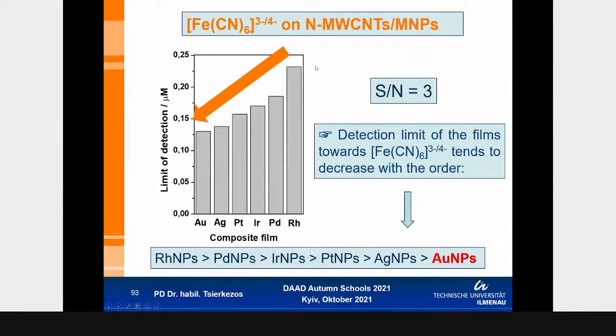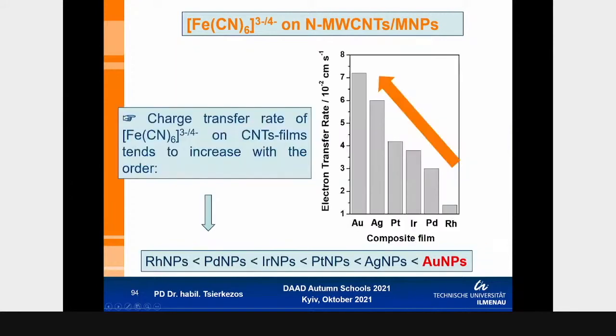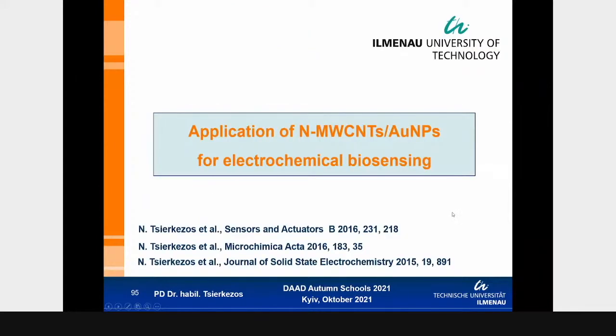And we have observed this behavior. The limit of detection tends to decrease from rhodium to gold, which means that within all the metallic nanoparticles which we investigated, it seems that gold helps best for improving the electrocatalytic activity. And also the gold helps for the kinetics. From all the metallic nanoparticles which we have investigated, the kinetics of the redox system tends to be better on gold compared to silver, better than on platinum and so on.